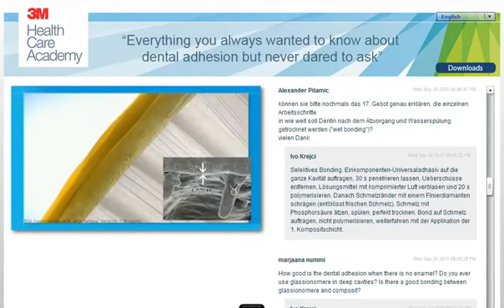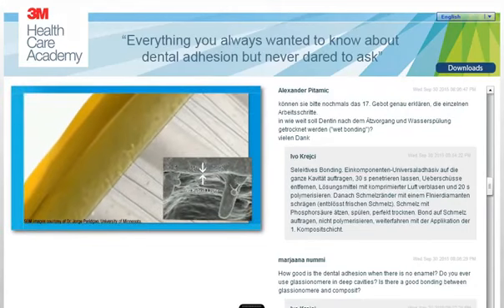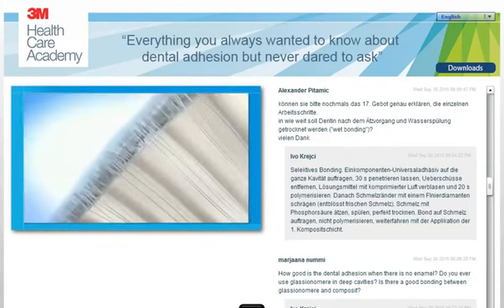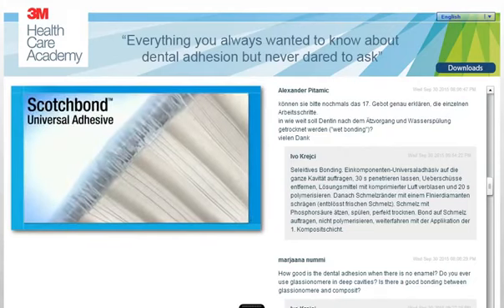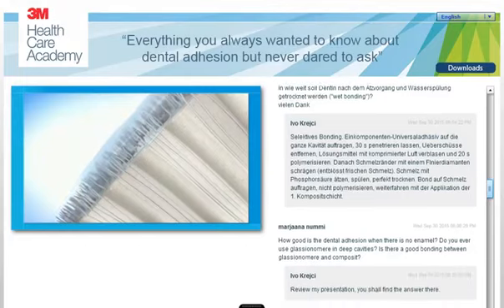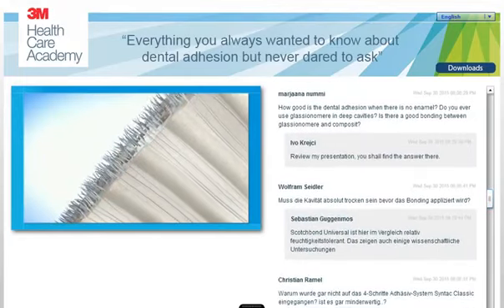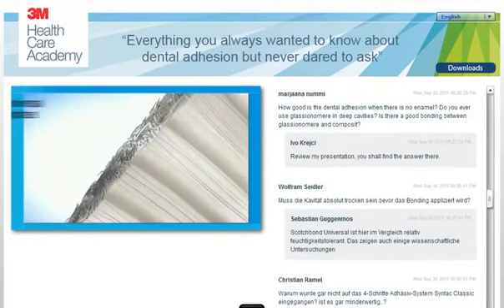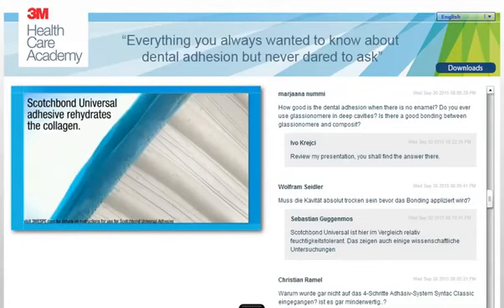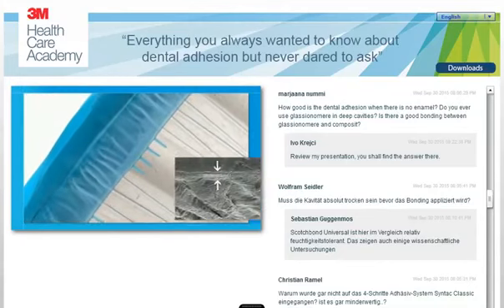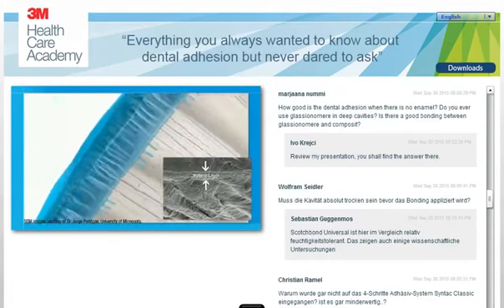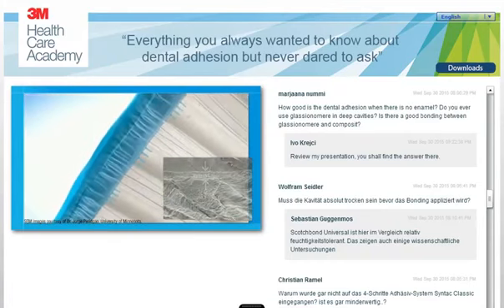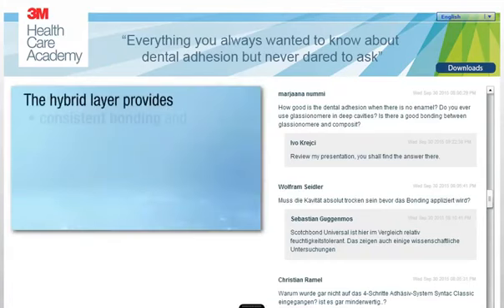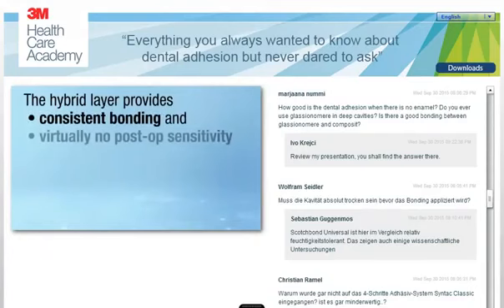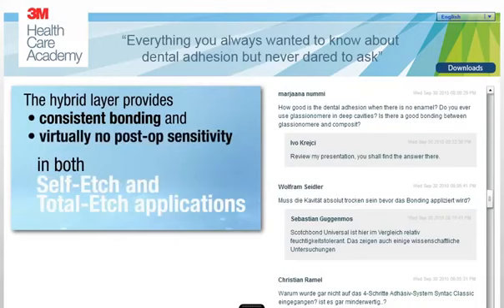That results in reduced bond strength and patient sensitivity. Scotch Bond Universal Adhesive is different. Its unique formula uses optimized ratios of 3M's patented Vitrebond copolymer, HEMA, and water to rehydrate the collagen network and form a distinct hybrid layer, whether dentin is kept moist or is dry. The hybrid layer provides consistent bonding and virtually no post-op sensitivity in both self-etch and total etch applications.